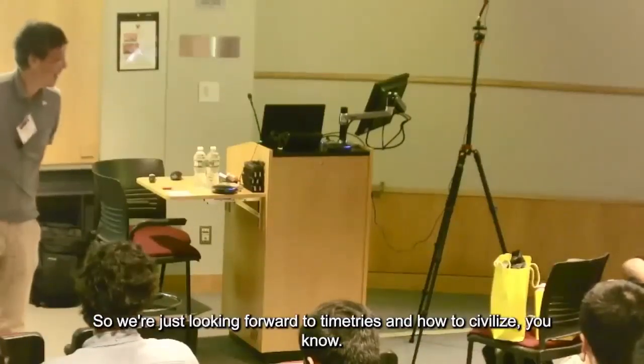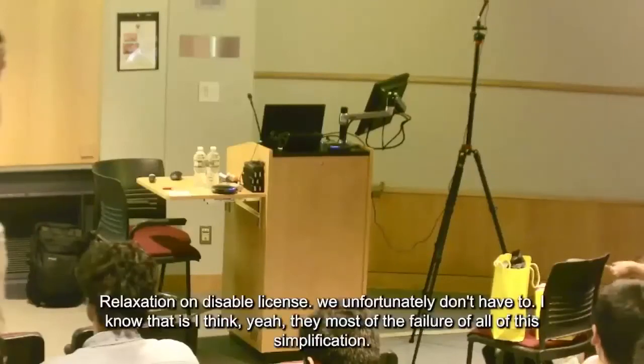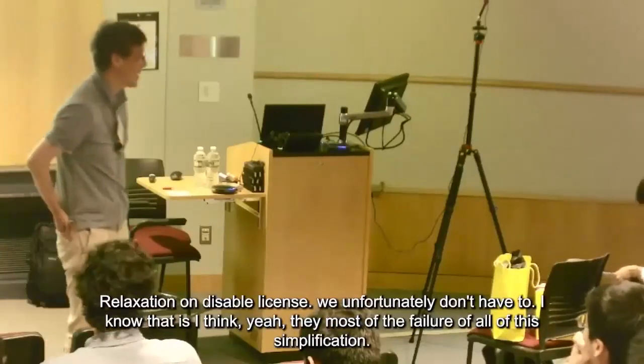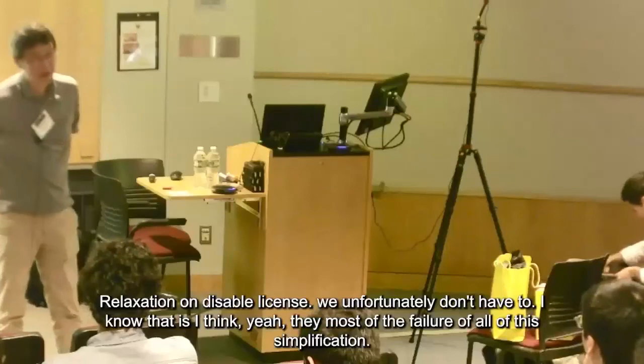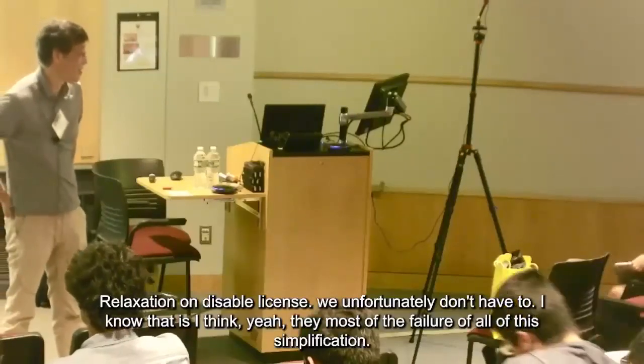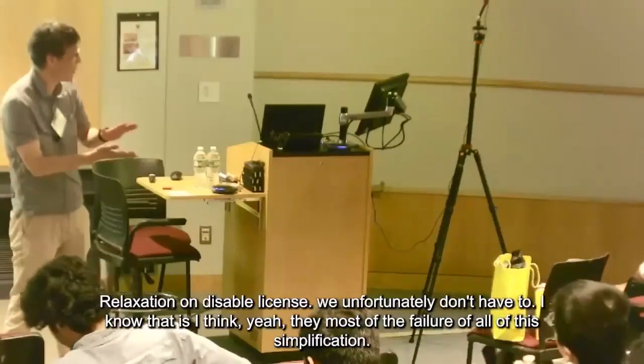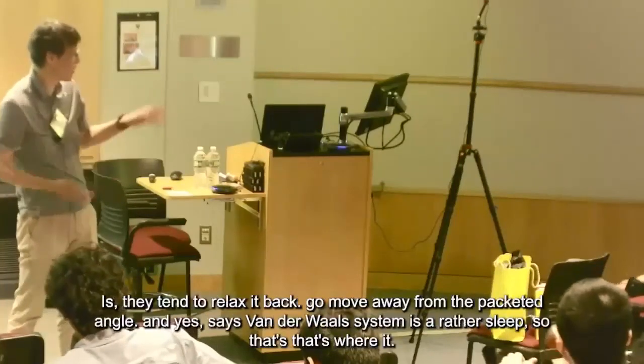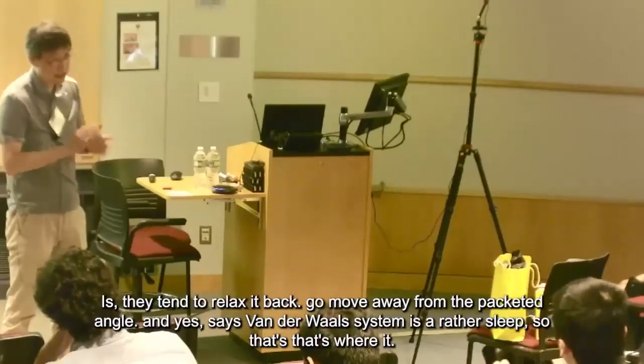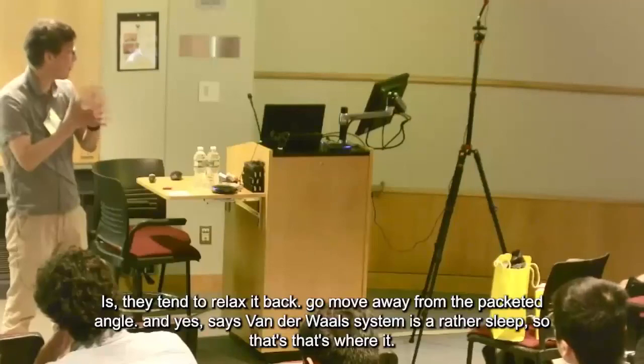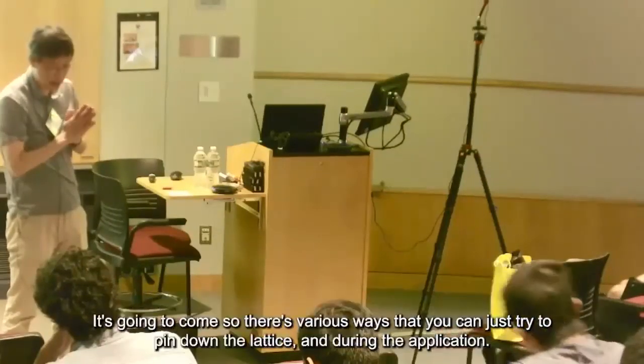Experimentally, we unfortunately don't have too much control. Most of the failure modes of sample fabrication are that the layers tend to relax back or move away from the targeted angle, and since the Van der Waals system is rather slippery, that's where the difficulty comes from.